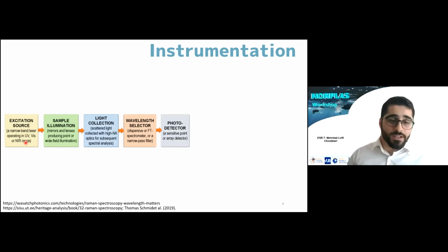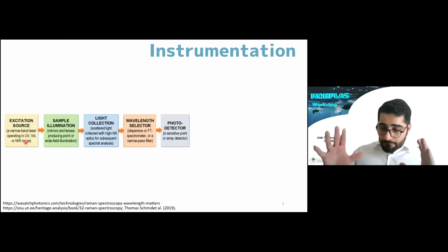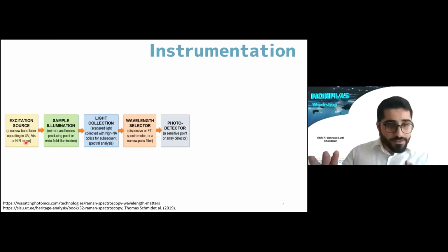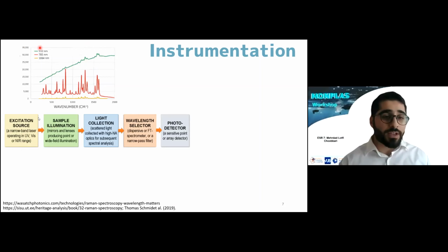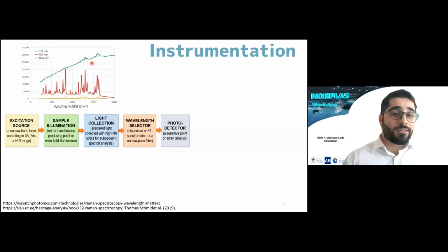And choosing the proper wavelength quite depends on your sample and the situation of your experiment. For example, here you can see the Raman spectra of a material obtained by 3 different excitation wavelengths. You can see that by having a short excitation wavelength, for example, 532, the green spectrum, the intensity of Raman signal is high, while we have a large background, which covers the specific peaks of the Raman spectrum of that material. By going into longer wavelengths, for example, 785, the red spectrum, you see that the features of the Raman spectrum of that material have appeared. On the other hand, the intensity is lower.